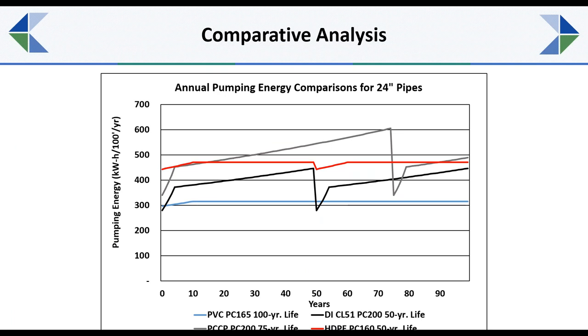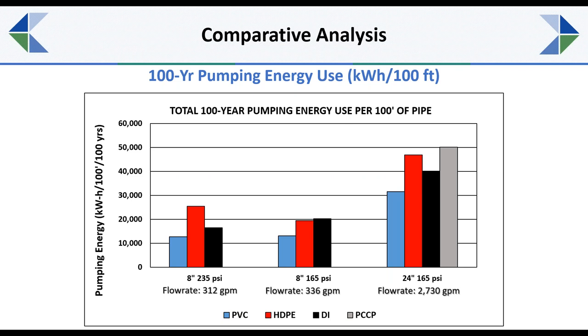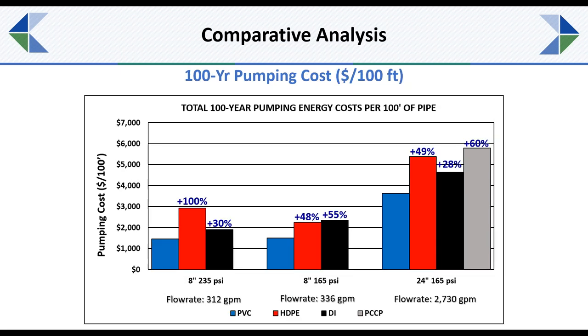So based on all of that information, we first determined what the pumping energy would be. This would be for the 24-inch pipe, like what you see here. So again, you start off at 0 years, but cumulatively building up over time, you see that the deterioration of the flow characteristics for the mortar and concrete lined products does start to affect them much more as they age. So looking at the total pumping energy for 100 feet of pipe for the different flow rates and sizes, you can see that PVC pipe does have one of the lowest overall pumping energy demands for that 100-year lifespan.